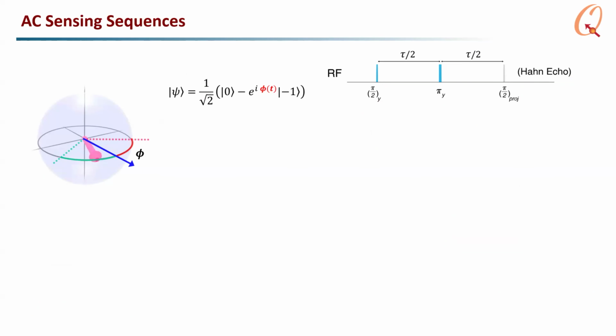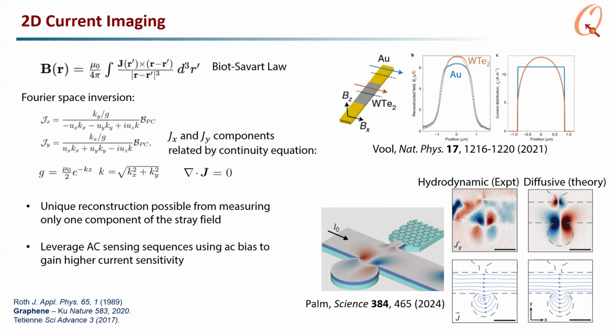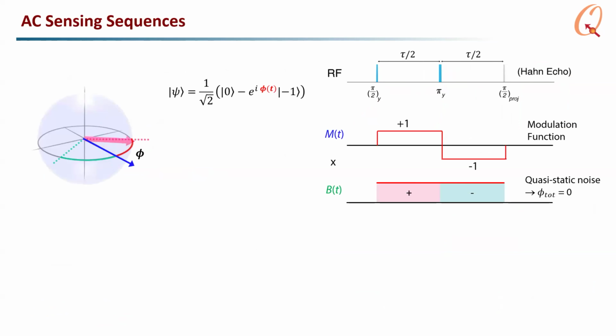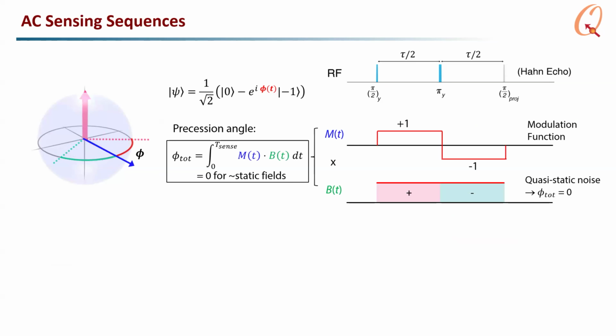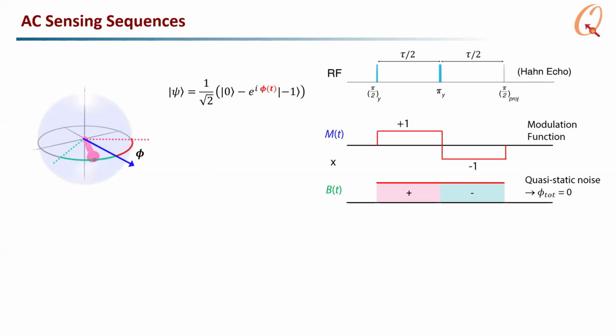Okay, and the other thing about current imaging is that you can use what's called AC sensing sequences. These sequences use so-called Hahn echo or dynamical decoupling techniques, where you're measuring the precession of the NV center on the equator. What you do is you put the NV center on the equator with a pi/2 pulse. You let it precess, so it's going to go around, and then you flip it around the x-axis, and then you let it precess again.